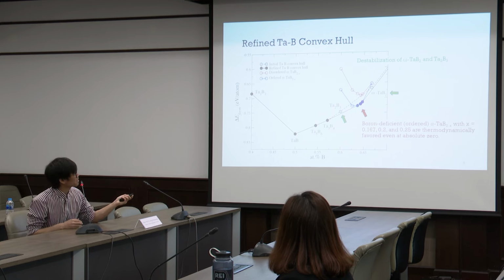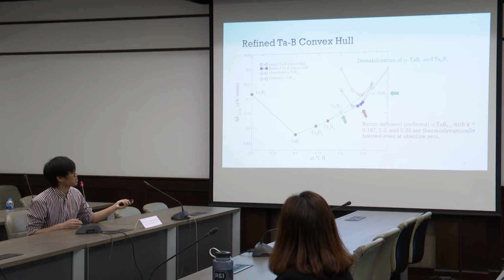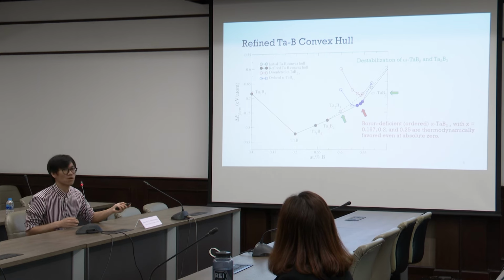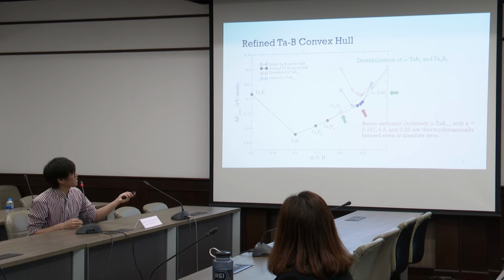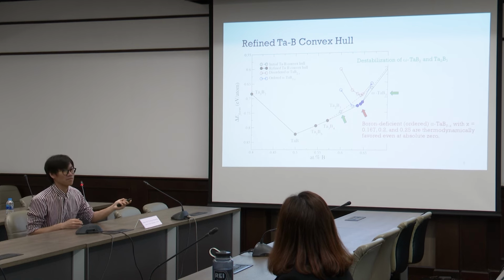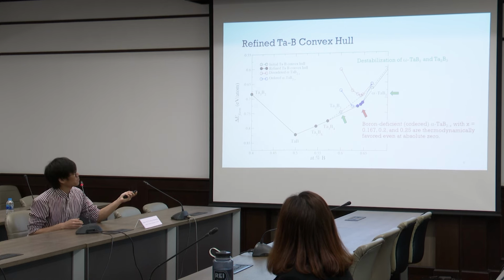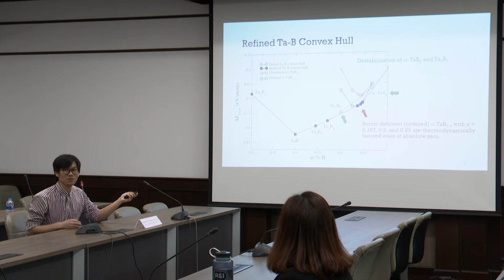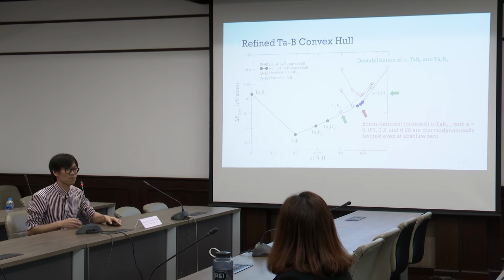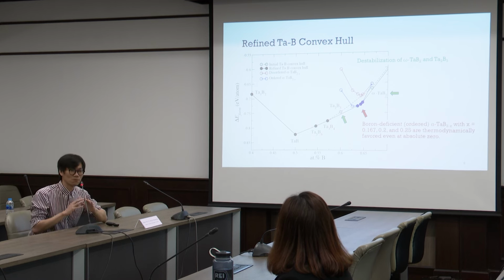What I found is that the boron deficient alpha phase of TaB2, where x can be some number like 0.167, 0.2, and 0.33, can lie on the ground state line. And because of the stability of this boron deficient TaB2, we observe the destabilization of the omega phase TaB2 and Ta2B3. What I found in this work can really explain the discrepancy that I mentioned on the previous page.